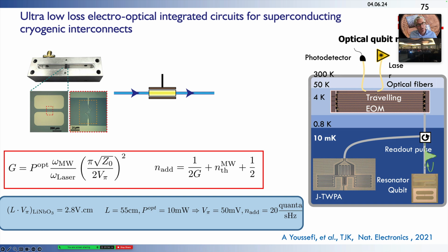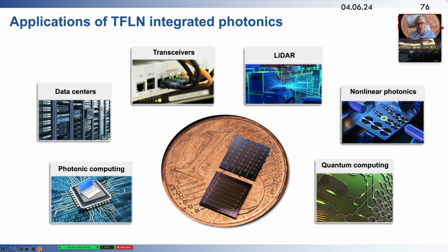And for this, what you need are very, very low loss modulators. And the only way to generate these is to actually make very long devices. And you can make modulators with a meter path length in lithium niobate, lithium tantalate on chip that have switching voltages on a level of a few tens of millivolts, which would then allow actually to create these optical transduction lengths.